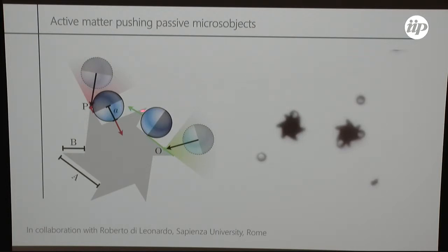So if we tune the shape or the geometry of the object that we give our particles to play with, and we have something like this gear here, if one of the sides of the arms of the gear is short enough that the particles can't really dock in there, but the other side is long enough that the particle can really swim in here and orient, then we can achieve a structure that can be very well rotated by our particles.